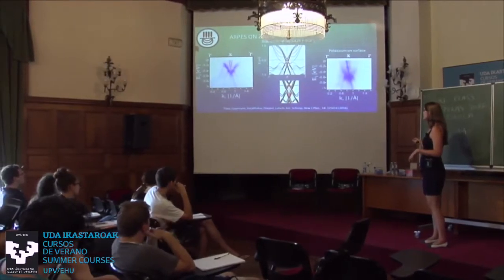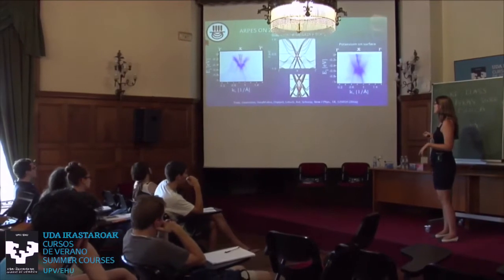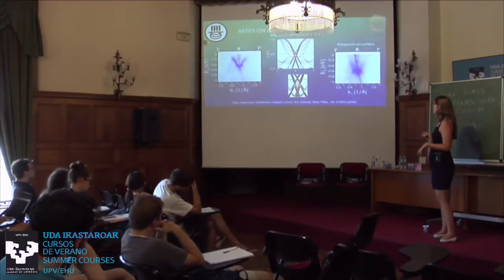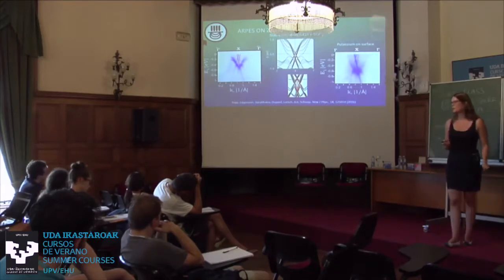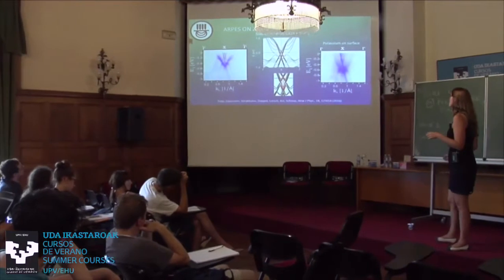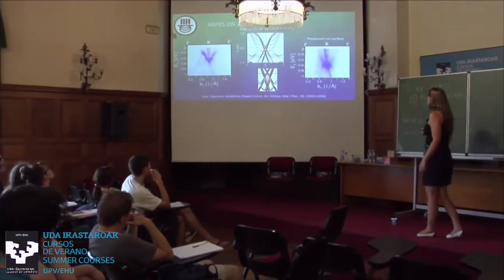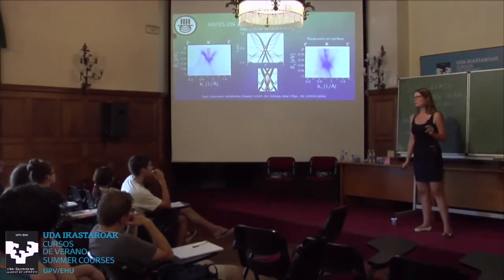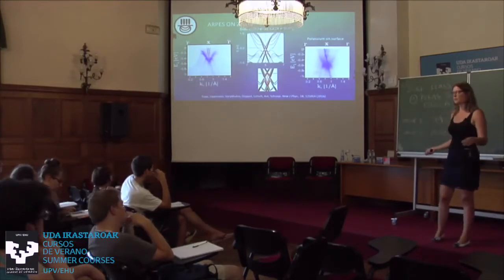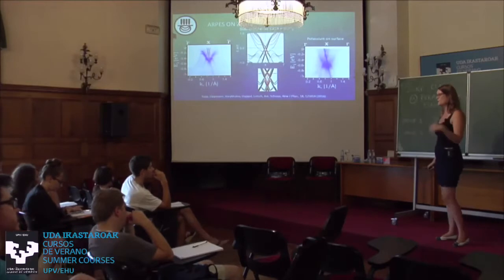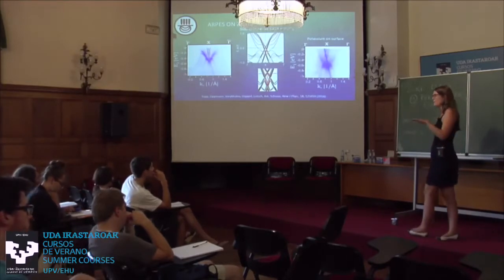So we took some cuts through the momentum space and compared it again with a slab calculation. The feature we're interested in is this red-shaped rhombus here, where the Fermi level cuts the upper non-symmorphic cone right here. And so we can see this feature in the ARPES data here, and we see our Fermi level is slightly lower than we hoped it was going to be, so the samples are slightly hole-doped. And so this is nice because then you can play a trick. You can just evaporate some potassium on the surface of a material, and potassium is very electropositive, so it injects some electrons into the surface of the material and therefore raises the Fermi level a little bit.